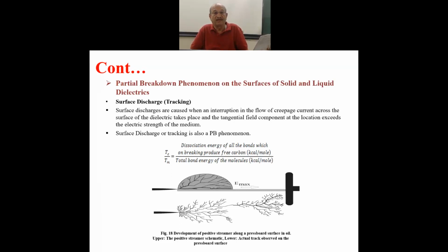As I said, if you want to experiment one day in your high voltage lab, you just take simple, cheap window glass, and put an electrode on the top, and on the bottom you put another electrode. The top one you apply the voltage, on the bottom one you just ground it, and you may increase the voltage to a few kilovolts, and you can see the surface breakdown taking place on the glass sheet or glass plate. So the simple window glass has a very high tendency to track. That is why it is not used for insulation purposes in electrical engineering.